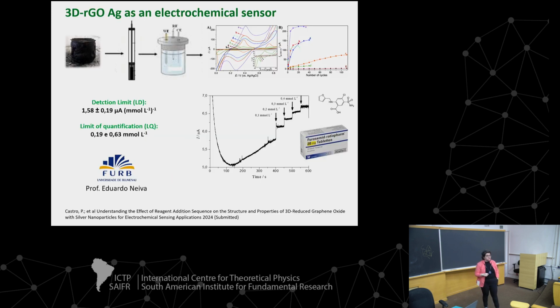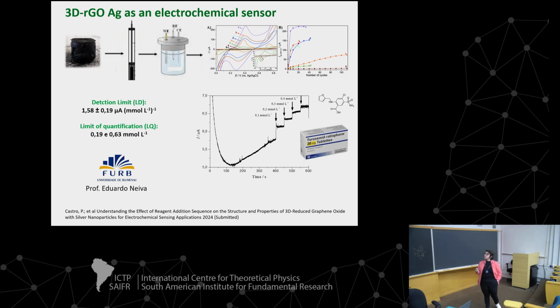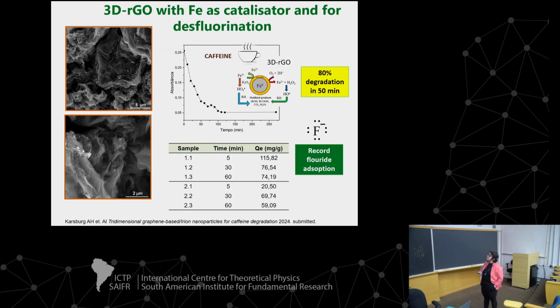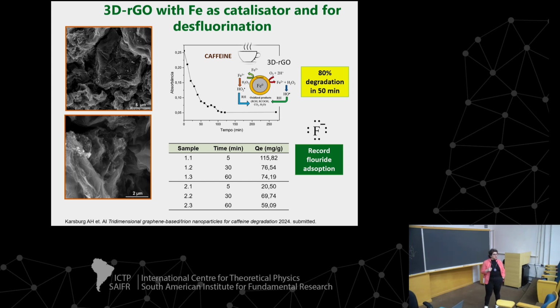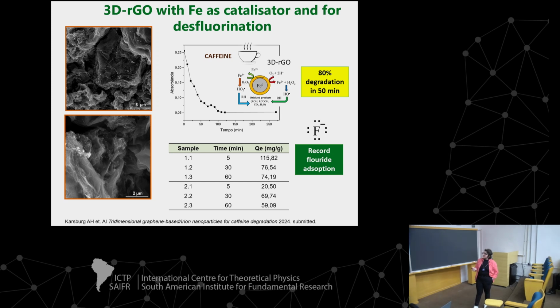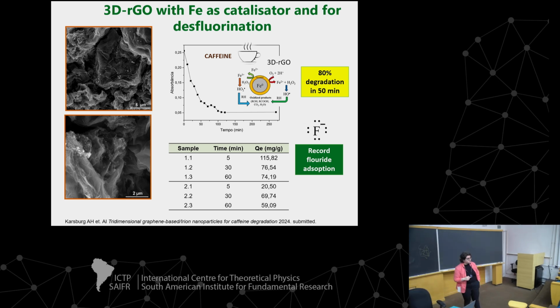These materials we tested for sensors to analyze contaminants like pharmaceuticals in low concentrations in the environment, and it worked very well with low quantification limits. Here, many of you saw the work of Bruna, my master's student, who used this kind of graphene decorated with iron. We tested this as a catalyst for degradation of caffeine, but now we are testing this material to remove fluorine. Fluorine adsorption, the first results show good records for adsorption of fluorine, but also we will need to understand why.